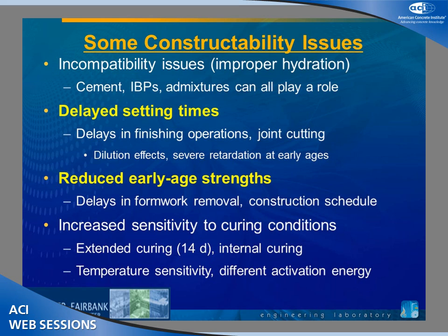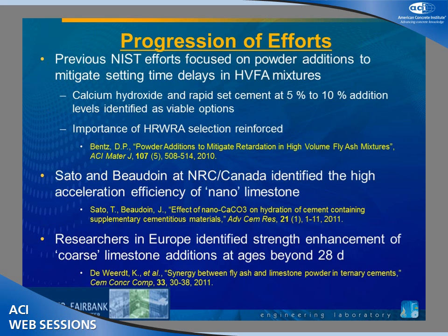And generally, they have a higher temperature sensitivity. Many state DOTs will say after October, you're not going to use fly ash, or you're going to use less fly ash in your concrete, just because we're not sure you're not going to get one of those cold days and the concrete's not going to set for 12 hours.